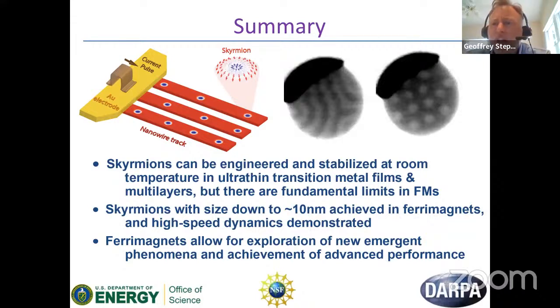We see a dependence on both. And so from our work, I would say it's difficult to ascertain at this point. What we don't see is the same mechanism as when you put platinum on cobalt. So it doesn't appear to be related to the spin orbit coupling, and that you could see from the experiment where we put copper on top. But there's a dependence on the metal, there's a dependence on the substrate.